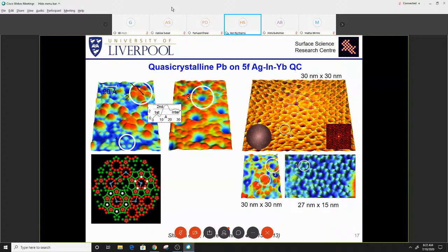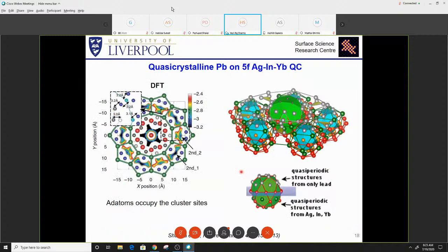And if you have enough material, you see a network of pentagons you can map using pentagon analysis. We always use Fourier transform analysis of this. This is the third layer and so on. Again, we asked our collaborators to check whether our interpretation is correct or not. And happily, the experiment was consistent with the theory, giving us confirmation. What is happening here is a simple picture.